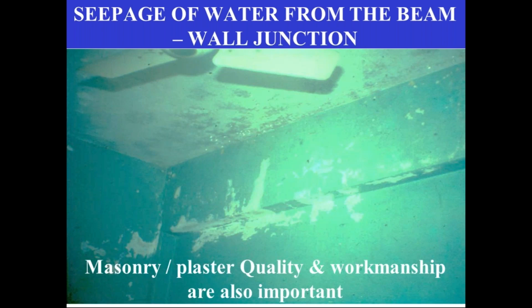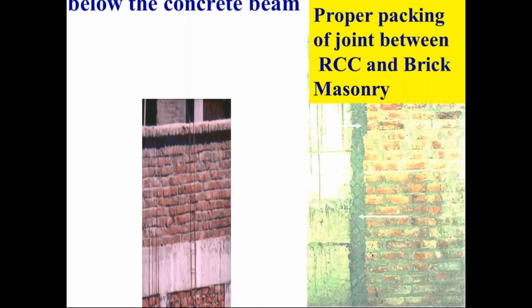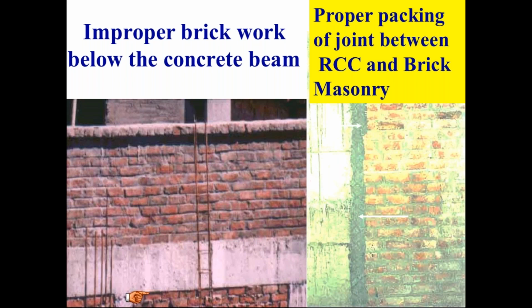here you can see on the left hand side the external face of the building, which the mason is not able to see and do unless he does the external plaster. My advice is that before doing the external plaster, seal all these openings properly, cure them for at least 3 or 7 days, and then do your plaster. This is very, very important.